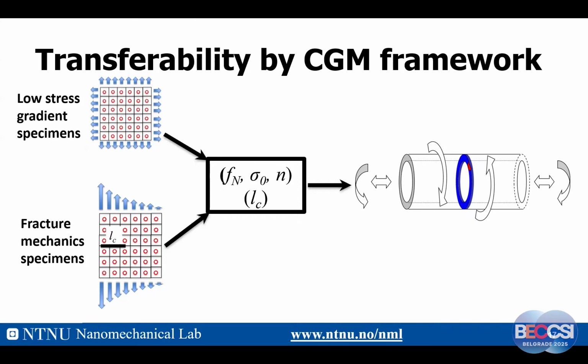That's the way of transfer from small specimens in the laboratory to large components in service conditions. So we have to have both a low stress gradient specimen and a high stress gradient specimen. Okay.